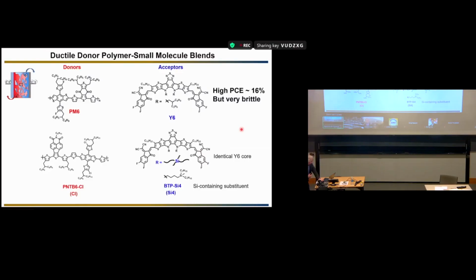Another way we did it is actually by changing the structure to a certain extent of the molecular material. So in this work, basically what we did is we take the same donor that I showed you before, the red phase, and then as acceptor we can use the classical acceptor which embrittles the blend, or we can use the second acceptor. For those of you who are organic chemists, the major difference between these two systems, they say, well, there is no difference. As a matter of fact, there is a big difference in the chain where you have this trialkyl-silyl substituent. And this makes actually a huge difference.